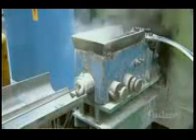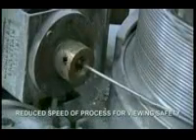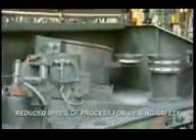The descaled rod is then drawn through a series of reducing dies by geared motor blocks positioned behind each reducing die. The number of dies used is dependent on the diameter of wire that is required. The wire rod is lubricated with wire drawing soap prior to passing through each die to reduce friction and ensure a good surface quality.